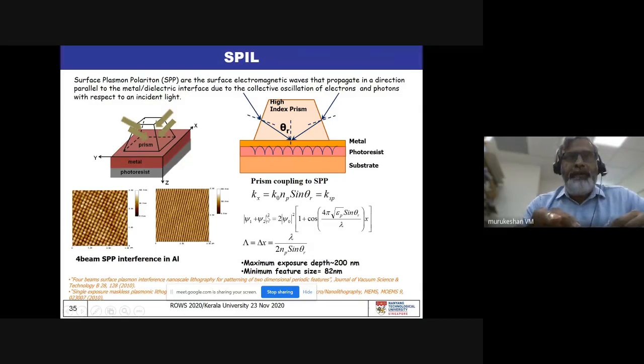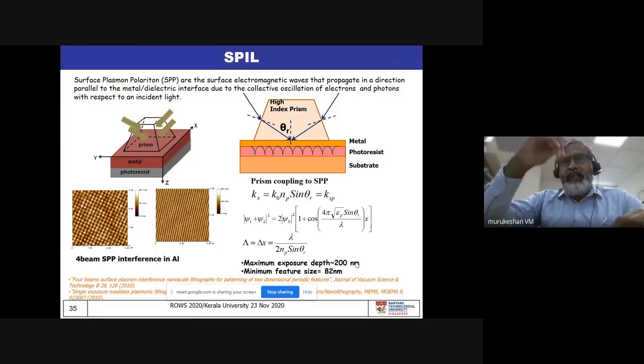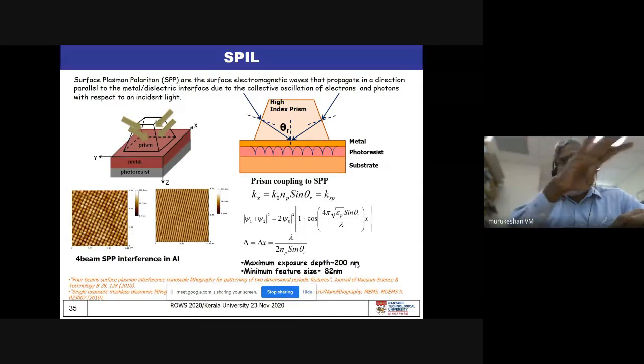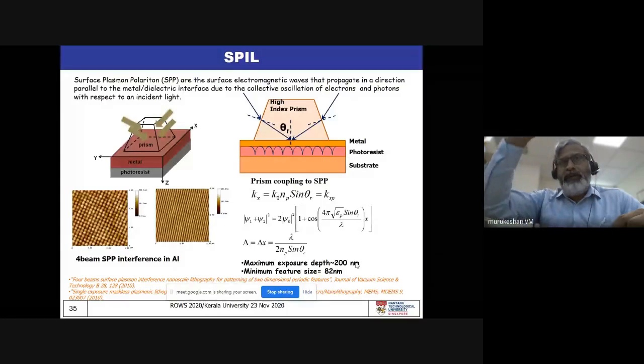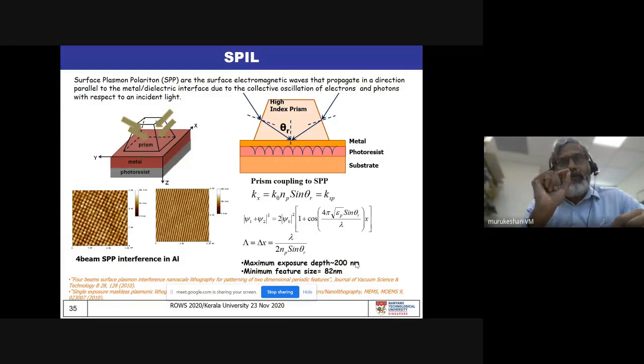And you can see that the pattern dimension that is observed is very, very interesting. We were able to achieve the minimum feature size to sub 100 nanometer, around 80 nanometers, and the exposure depth is 200 nanometers. What is the significance of that? It means that in the previous case, with the evanescent wave patterning, we were not able to get this high pattern dimension. But when we use plasmon interference, we were able to not only get the smaller feature size, but also achieve high aspect ratio.